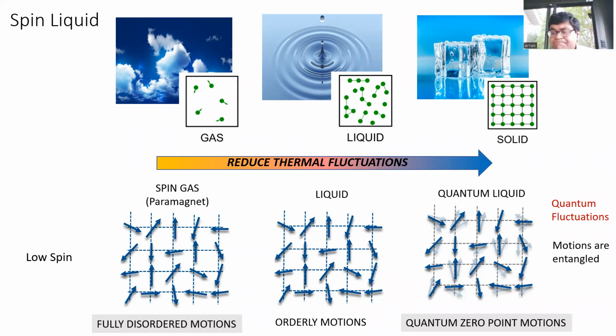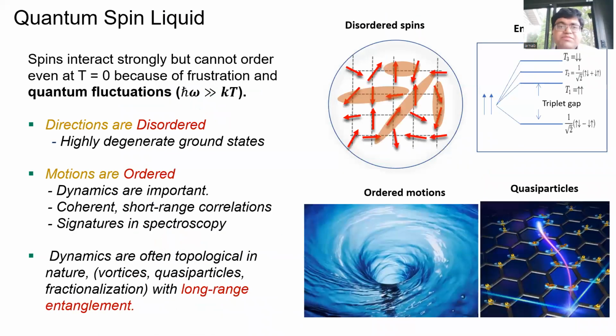The reason why you get no ordering is because of quantum zero-point motions. And that's what you have in a quantum spin liquid: even if you lower the temperature to absolute zero, and even if there are very strong interactions between the spins, they cannot really order. So what we understand from quantum spin liquids is that it happens when quantum fluctuations are very high, and they are higher than the characteristic temperature of the system.